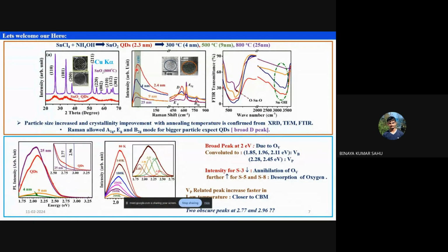Those who are well acquainted with the experimental side can enjoy the slides. Others, for the time being, can just see the actual result and the interesting part. This is not very interesting. These are the XRD of the quantum dots, and this is the structure. This quantum dot was again annealed at 800 degrees Celsius to make bigger particles of 25 nanometer size. So this is the XRD of the bigger particle, and this is the XRD of the smaller particle.